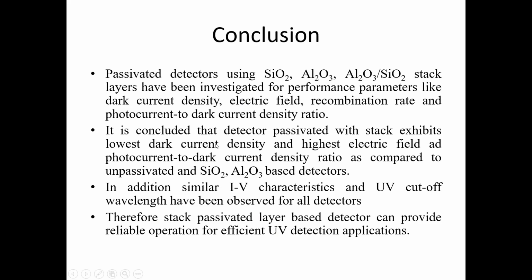After simulation of all parameters of the considered detectors, we have concluded that the detector passivated with the stack exhibits the lowest dark current density but the highest electric field and photocurrent to dark current density ratio, as compared to unpassivated and single passivation layer based detectors.